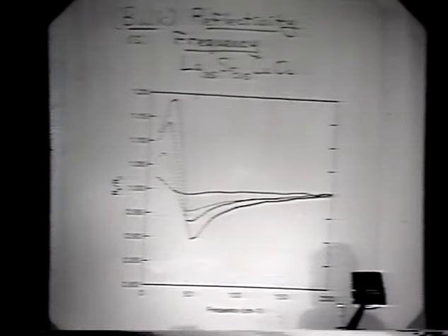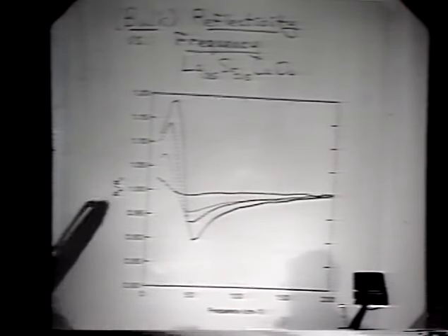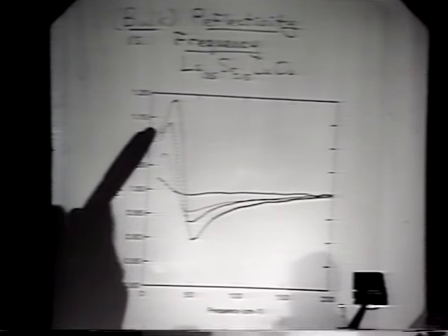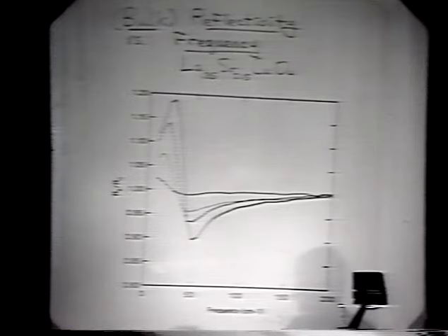Tunneling into thin films produces similar results, similar estimates for the gap. Now, we've also looked at the gap by infrared measurements. Primarily, we do this by reflectivity from a nominally smooth surface. Here, we show as a function of frequency the ratio of the superconducting to normal reflectivity, and you see below the gap, the superconductor is highly reflecting.